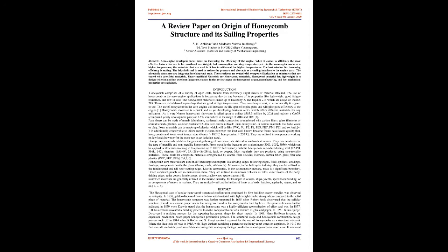cork. Foam materials can be made up of plastics like PVC, PU, PE, PS, PET, PMI, and so forth. It is additionally possible to use metals as foam, but that isn't well known because foams have lower strength than honeycombs and lower working temperature. Foams, 180 degrees Celsius, honeycombs, 250 degrees Celsius. They are used in components working under low loads, but for the most part as an insulating panel.